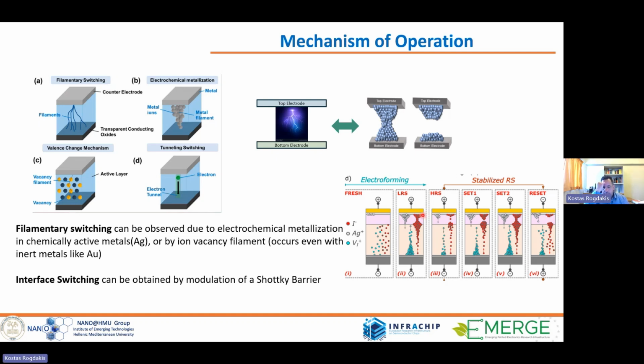by applying some electric field, actually, you induce a migration of some ions in the system that create some vacancies, and these vacancies that are left behind are conductive. So you form something like a conductive path. What do we call this? We call this a filament. So this filament, this conductive path, is actually behind the low resistance state. And when you reverse the polarity of the electric field, you suppress this filament, so you end up in a high resistance state. So roughly, this is the mechanism.